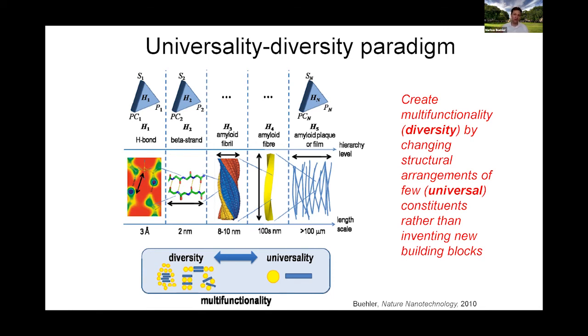And so it does a couple of different things. One, it makes it more difficult energetically to make a crack actually propagate through the material. And it also makes it less catastrophic when it happens, because you allow fracturing to happen all the time, but just not enough to break the entire material. This is the paradigm we see implemented in nature in these biological composites, including the conch shell. It's a very powerful way of creating very resilient and very robust materials.